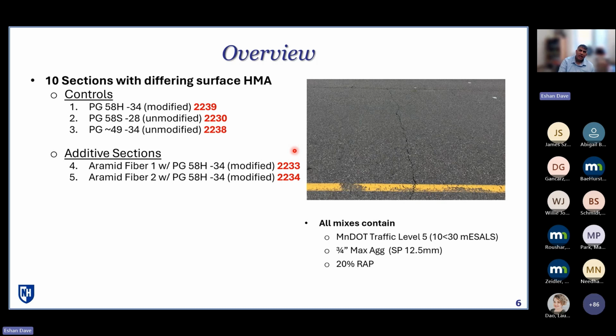Now, as it happens for the plastic and the rubber modified mixes, just starting off of that 58 minus 28 or minus 34 would result in those mixes getting excessively stiff very quickly. And so a 49 minus 34 unmodified binder was necessary to use those type of additive products. And since we were going to have 49-34 modified mixes, it was decided that we should also have a control section that's made with that same bitumen source, same binder source, as is used in case of some of your plastic and rubber additives. So cells 36 and 37: 36 is modified with a dry plastic additive, 37 with a dry rubber additive.